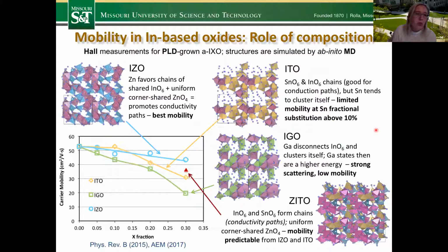And we also have done it for some other materials, such as indium zinc oxide, indium tin oxide, or indium gallium oxide. So here, these are the experimental results of the carrier mobility as a function of the doping, so the fraction of the X element, tin, gallium, or zinc. And just looking at the structure, we can tell that zinc favors chains, and that's why it has the best mobility overall. Tin actually helps a little bit, but only up to 10%, because after that tin tends to cluster itself, and so that's why we have a limited mobility.